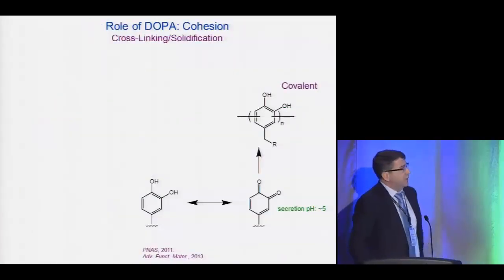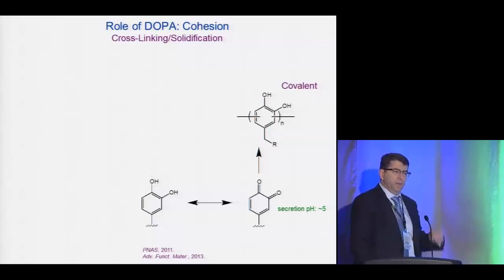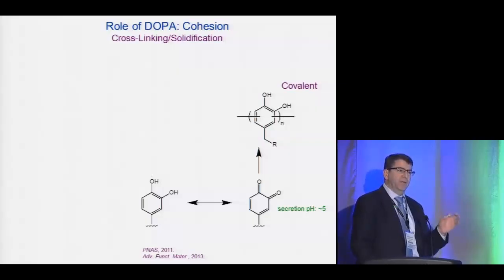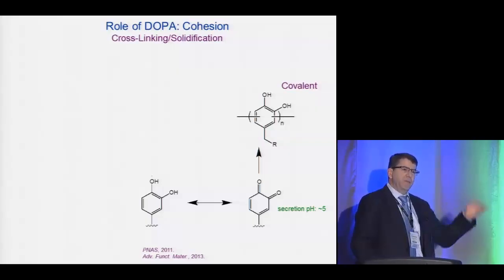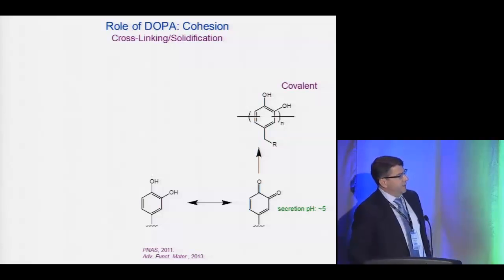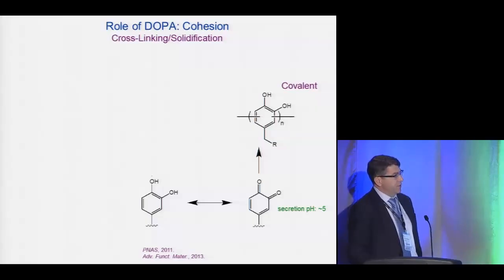The second role for DOPA is in cross-linking. DOPA provides essentially the cross-linking chemistry to drive the liquid to solid transformation in the adhesive. Remember that the byssus structure is secreted from liquid protein precursors, and in about 3 minutes it solidifies. And the chemistry underlying all that is due to the presence of DOPA. And this is the equilibrium I already described with the quinone. And when the quinone forms, it will cross-link with other DOPA molecules to form protein crosslinks, and this gives rise to a liquid to solid transformation.